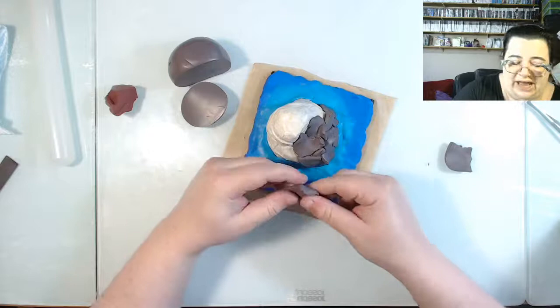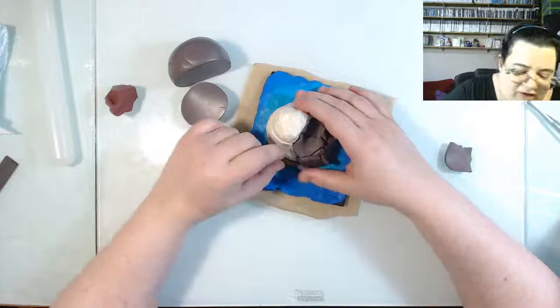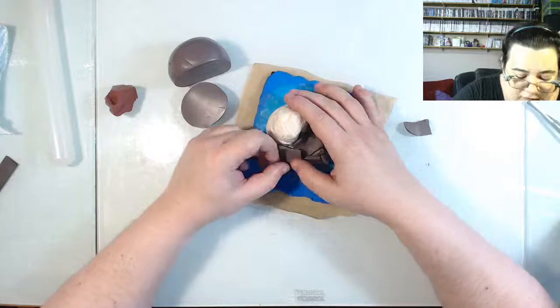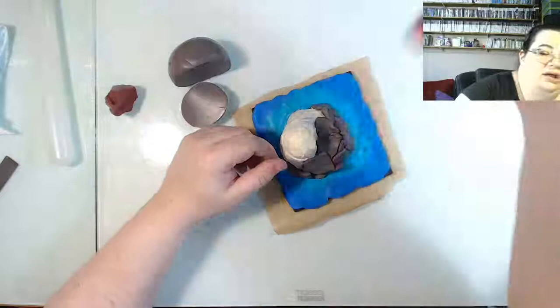And I'm not even sure how that will bake, because I'm sure it would do something to the reaction. I know putting too much baby oil in your clay can mess it up structurally, let alone PVA, which I think has quite a high water content if I'm not mistaken. And polymer clay hates water. It is not traditional ceramic clay. It is in the plastics family, and if you try and soften it with water, you basically ruin your clay. So what you soften it with is either a really tiny, as sparing as you possibly can, bit of baby oil, or what I use, liquid polymer clay, and that you haven't got to be so sparing with, because it's the same chemical composite as the clay you're starting out with. That make all sense?